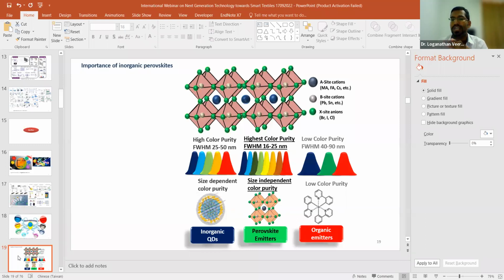What are perovskites? Perovskite is a normal mineral. And why do we need perovskites? Perovskites are cheaper compared to other materials we use in conventional methodology, they are easy to process, and the preparation method we can easily fine tune. Previously, we prepared semiconductors just by vapor based methods. Now if we employ these mineral based perovskite materials, it is possible to switch from vapor based to solution based. Solution based techniques are encouraging, because we avoid the large energy input needed to make the vapors, and then we have to control those systems, which are very expensive. If you want to overcome these things, you should rely on solution based techniques.